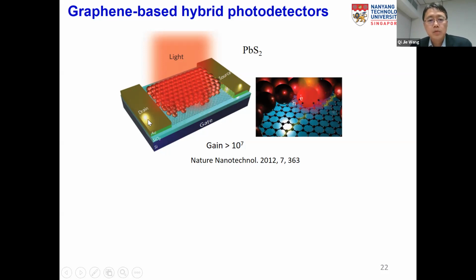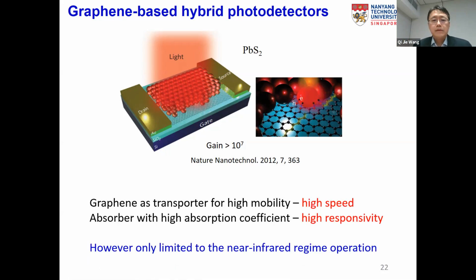And because here you apply voltage across the source and drain, the carriers in the graphene will circulate, right? And the other carrier in the nanoparticles has a relatively long lifetime. Therefore, the carrier in the graphene can circulate many times before they recombine. So this can generate significant photo response, and in fact can produce a very high gain. In this paper, up to 10 million is demonstrated. Okay. However, as I said, it only operates in the near infrared region because there's no narrow bandgap nanoparticle available.